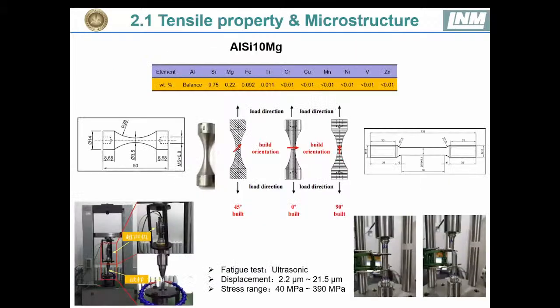And then here, as we mentioned before, in our analysis, an aluminum alloy is studied. The chemical composition of this aluminum alloy is shown in this table. This aluminum alloy is manufactured in 3 different directions: 0 degree build, that means horizontal build, 90 degree build, and also 45 degree build. Here we show them in these 3 figures.